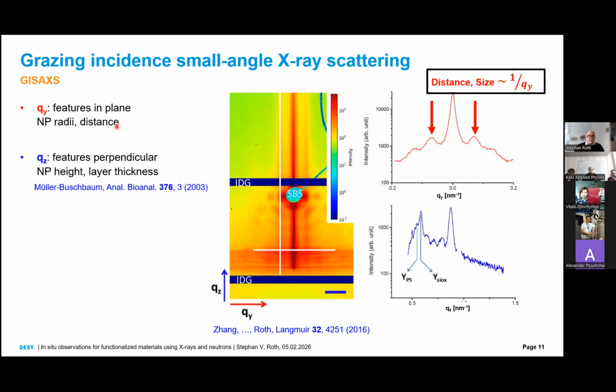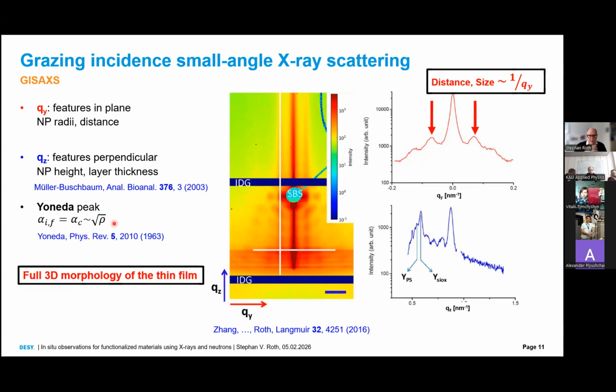If we then look in the vertical direction, we find again maxima and minima. These are the fringes stemming from the height of nanoparticles or layers. And we see here an interference phenomenon, which is called the Yoneda peak, and its position is characteristic for the material present. It's the angle of total reflection, keeping in mind that the refractive index for materials in the X-ray regime is smaller than 1. So vacuum has 1 and each material smaller than 1. This means if I shine my X-rays under a very low angle onto the surface, they get totally reflected, and you measure this position on a detector and you can deduce the density of the materials present in the sample. And all this allows you then to get a full three-dimensional morphology picture of the thin film.